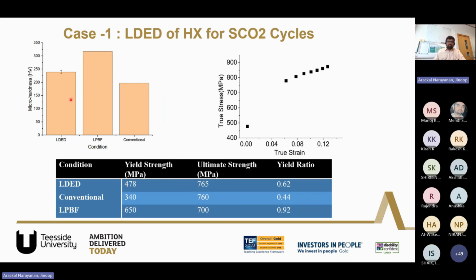Then we could see the mechanical properties are higher than the conventionally built samples, but slightly lower than the powder bed fusion samples, mainly because of the higher hardness and the fine grain structure that you observe for the powder bed fusion sample as compared to the DED samples. So DED is slightly inferior to powder bed fusion, and it is superior to the conventionally built samples. But if you consider ductility as an important factor, then conventionally built samples are superior to both DED and powder bed fusion.